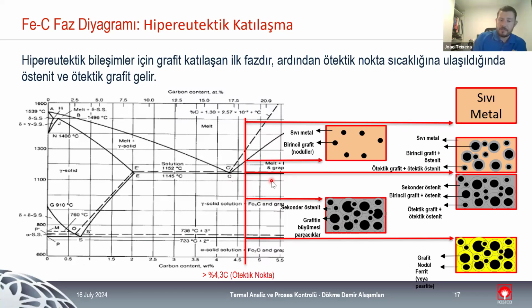So if we need, for some reason, to use the expansion of graphite at this stage, we don't have a lot of carbon in the melt for that to happen. So we have problems like shrinkage and micro shrinkage because we use a type of solidification that was not adapted to the gating system or the type of cast that we are going to produce. And after the eutectic level, we have exactly the same as for hypoeutectic. We have a mix of austenite and graphite being formed and growing until we have the cast completely solidified.